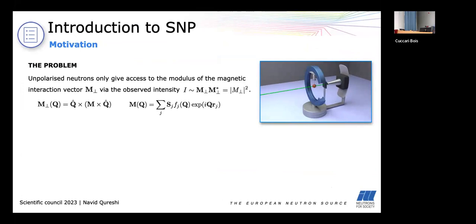Most of the magnetic structures are derived by unpolarized neutron diffraction either on powder or single crystal samples. But in both cases you have the problem that you're only sensible to the modulus of the magnetic interaction vector by measuring the intensity of a magnetic Bragg peak. This is a vectorial quantity, so by measuring the squared modulus we obviously lose a lot of information which we only can recover by measuring tens or hundreds of reflections and sometimes that's not even enough.